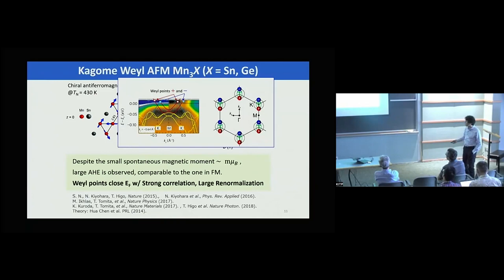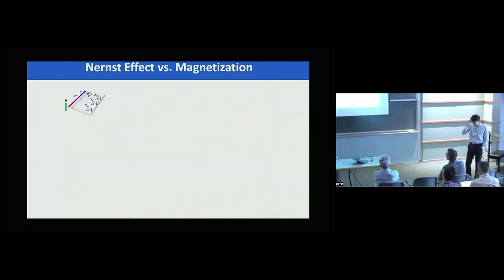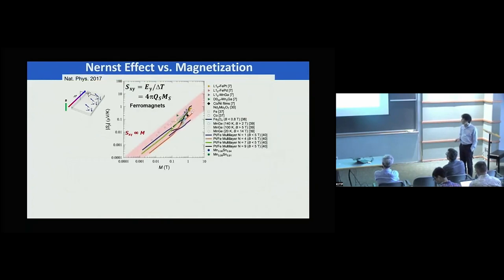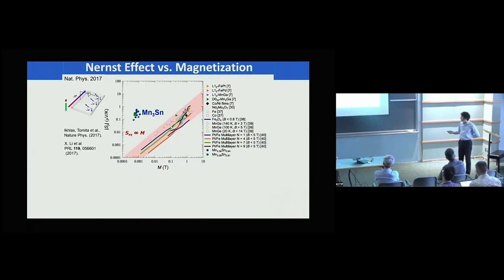So there is a strong correlation effect due to the manganese 3D electrons. Another important point is the thermal transport analog of the Hall effect, which is the Nernst effect. And this is again another magnetization scaling. For manganese tin, because of this 120-degree order, there is only a tiny magnetization of a few millitesla. So you wouldn't expect any Nernst effect, but it actually turned out to provide a very large one, nearly the maximum size known for a ferromagnet.